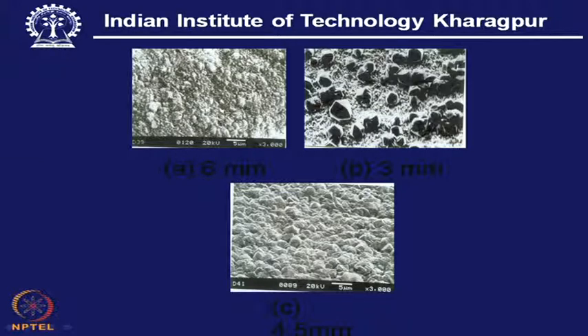However, here we do not have such a favorable situation. This is a very adverse situation. The outcome is that it is not fully grown, and it looks like the crystals have not grown at all. So, it is something very much towards the amorphous side. Just by looking, one can find out the difference between these two. So, we have to train ourselves so that these two images can give us the message that yes, this is one good coating, well developed, and this is a poorly developed morphology.